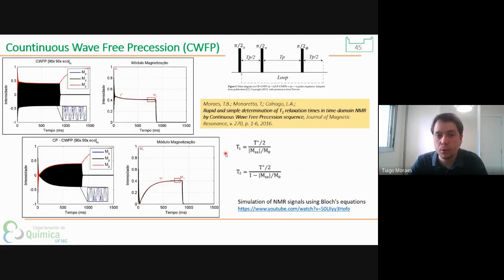There are other pulse sequences that we use. Here I will show some pulse sequences that Luiz Alberto Colnago uses a lot at Embrapa, as Marcos said. He has been developing some new methods in low field NMR. This pulse sequence, continuous wave free precession, as I show here, is a block of 90-degree pulses with some different phases and times and spaces. But what we produce with this pulse sequence is that the magnetization goes to a steady state, as you can see here.